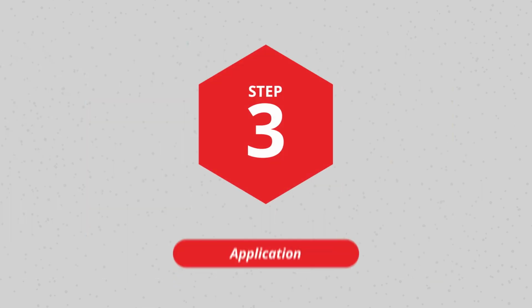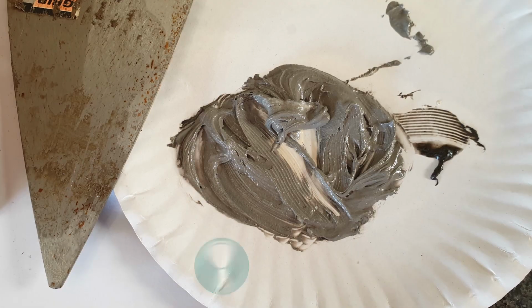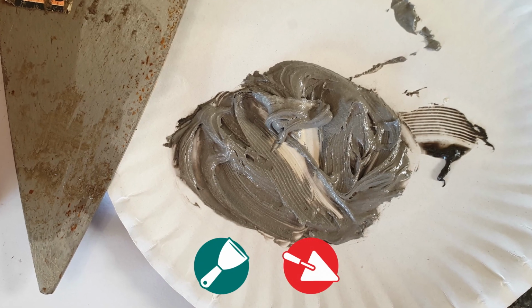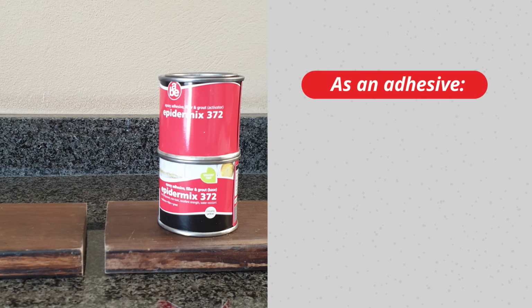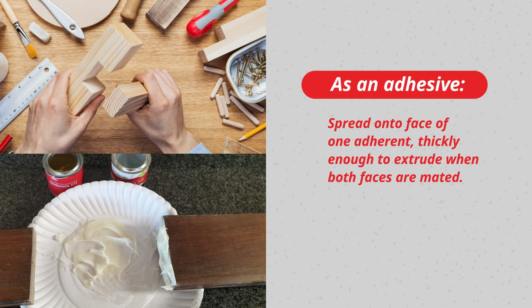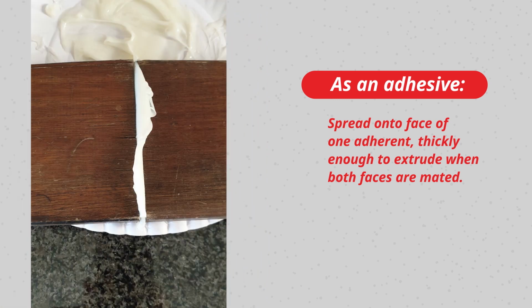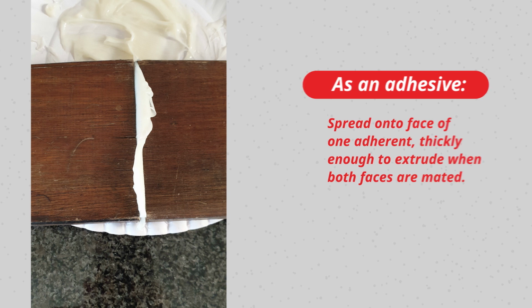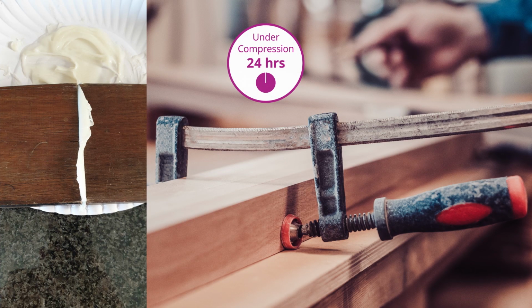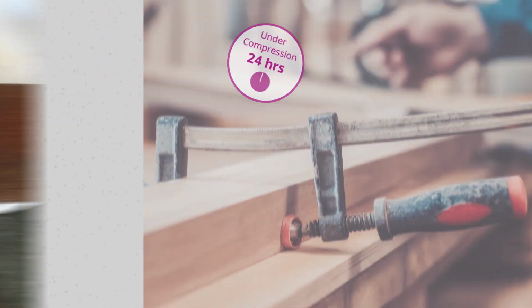Step 3. Application. Make use of a putty knife or trowel to apply the mix. Epidermix 372 as an adhesive should be spread onto the face of one adherent thickly enough to extrude when both faces are mated. Bonded mating faces must be kept under compression until the adhesive layer has set.